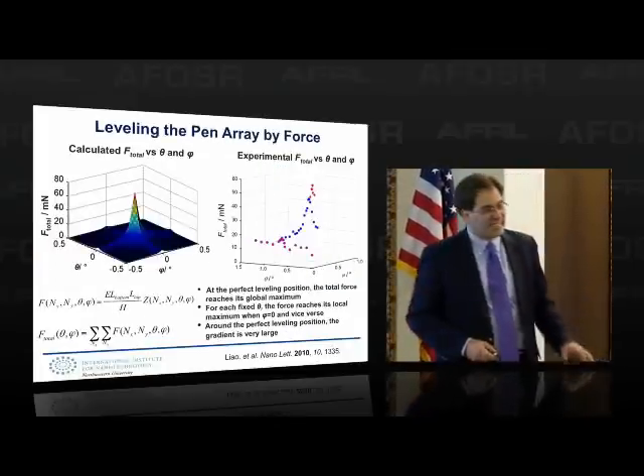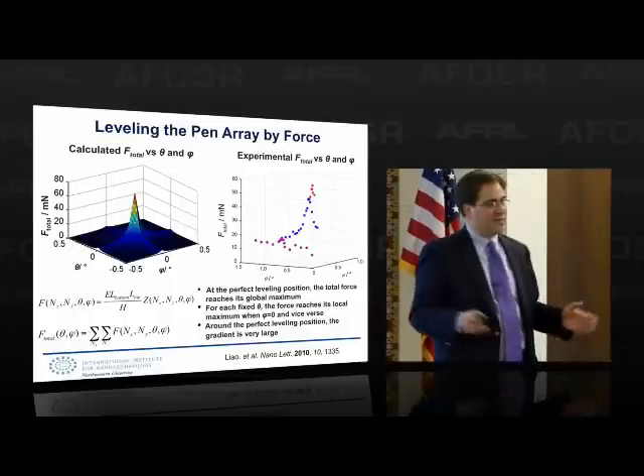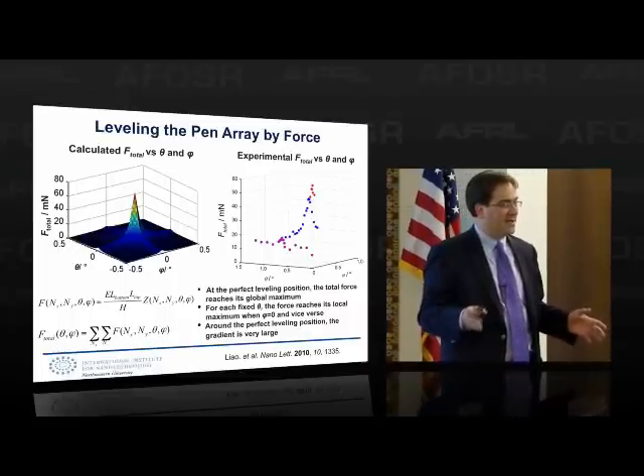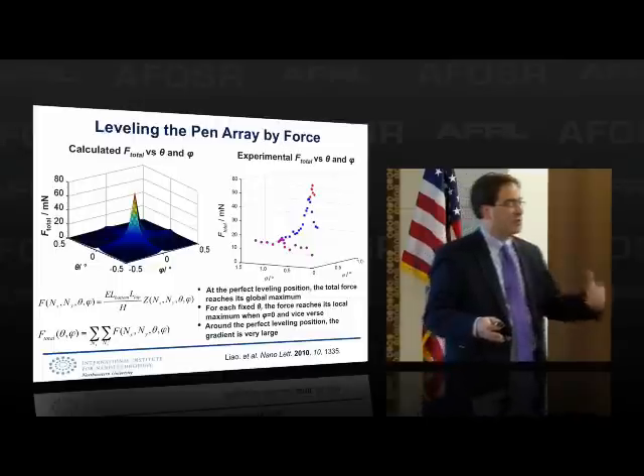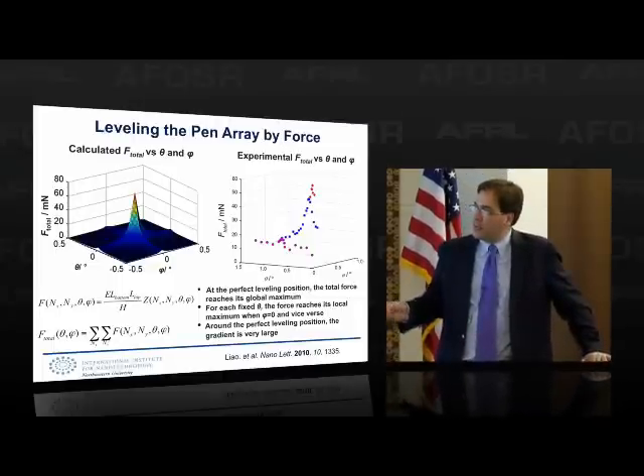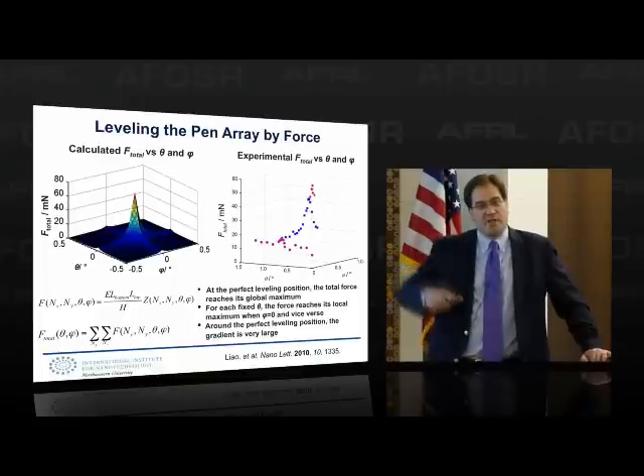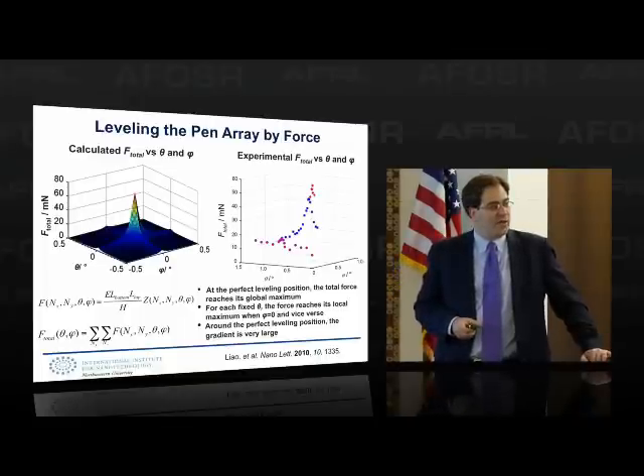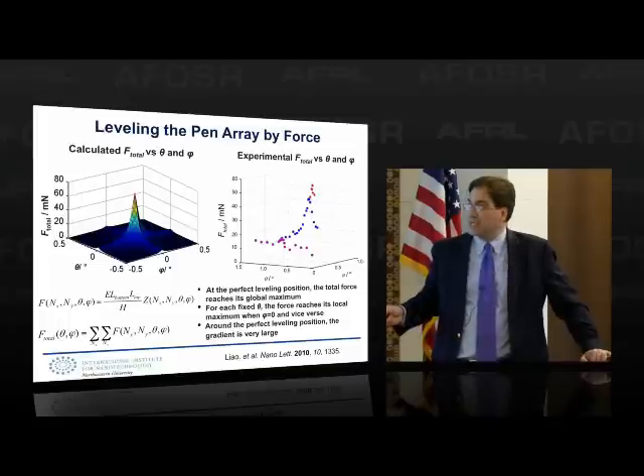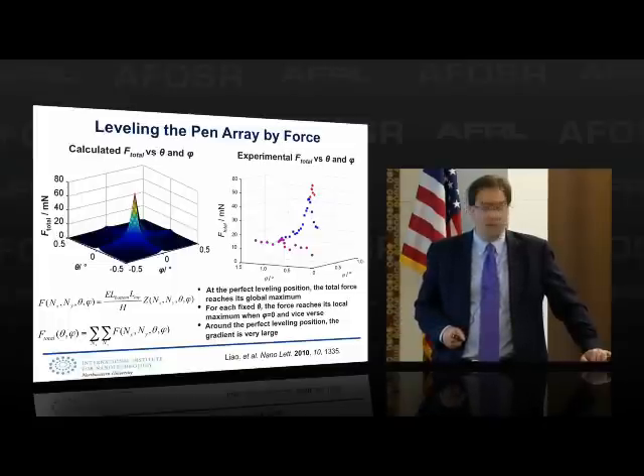Okay, so we said it'd be really nice if you just didn't have to have a guy who had a real green thumb to do this, and you could make this something that was almost programmable. And so we began to model when there would be the greatest contact force. And it turns out it's when the array is perfectly level. When all the tips are in contact with the surface, that's where you reach a global maximum in terms of contact force with the surface.